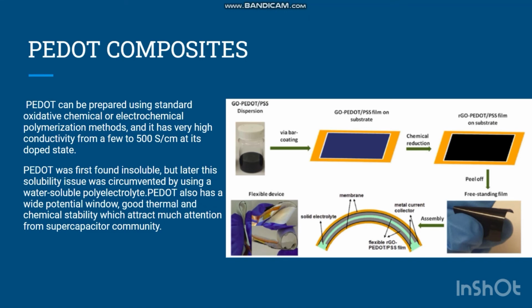it has excellent cycling stability with over 80% capacitance retention over 70,000 cycles, unlike the PPY film. However, one disadvantage of the PEDOT supercapacitor is the large molecular weight, which leads to a low specific capacitance. In order to minimize the aggregation of graphene nanoparticles in the composite, a method similar to the PANI polymerization method can be used to form the graphene PEDOT composites.